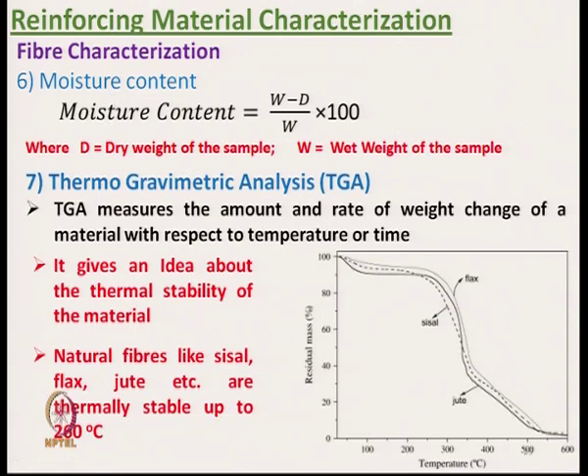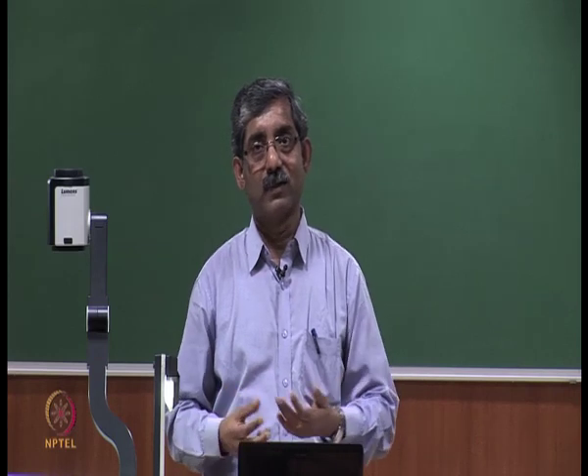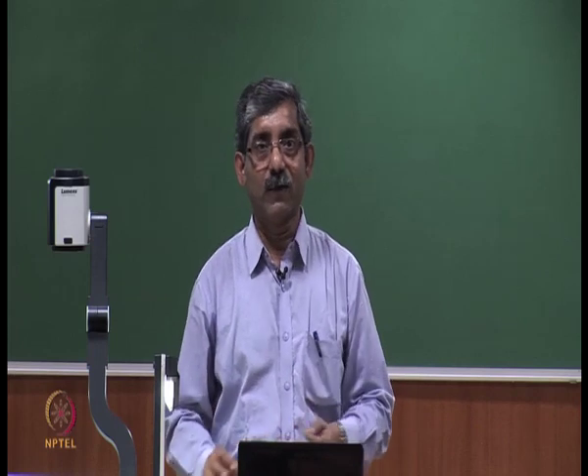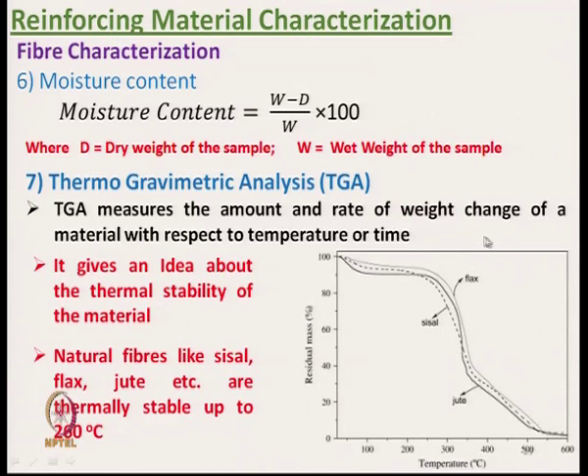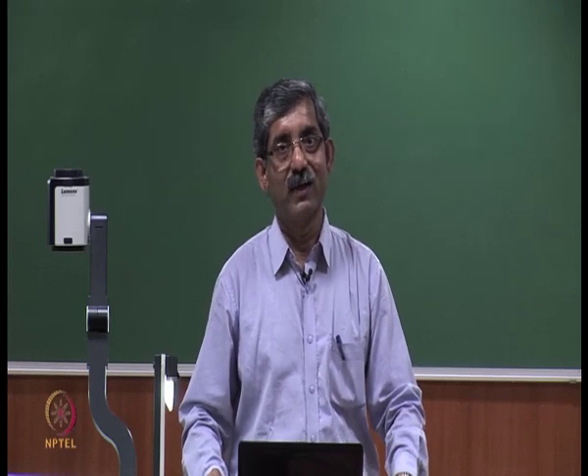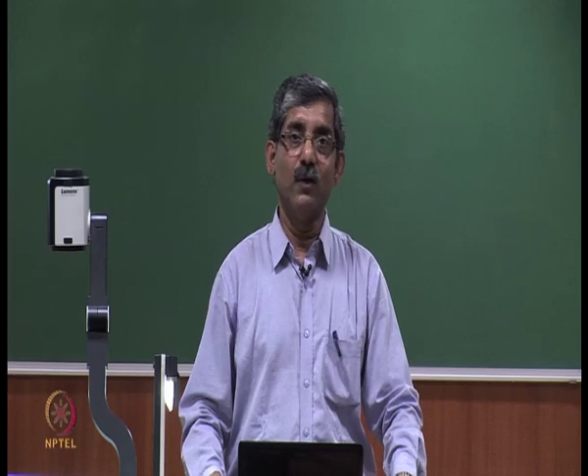Another test method for reinforcing material is thermogravimetric analysis. This is a very important property, where it shows the change of mass, change of weight during heating. Okay. TGA measures the amount and rate of weight change of material with respect to temperature or time. So, in x axis this is showing the temperature, and in y axis the residual mass. So, once the material is heated at very high temperature, the material loses its weight due to internal structural change, internal decomposition. So, that will show with this curve.